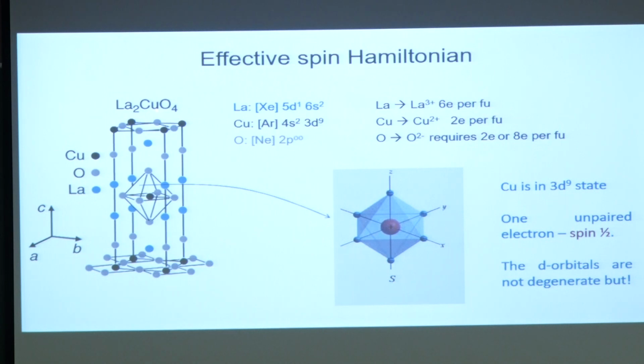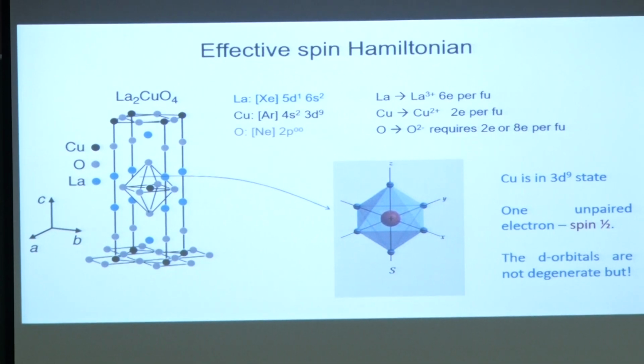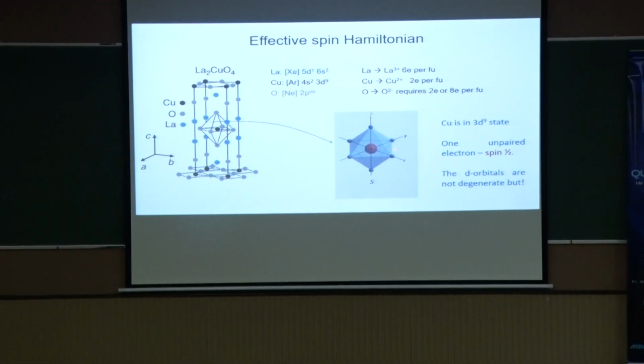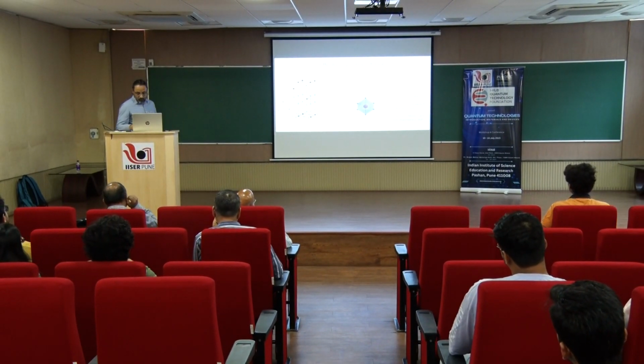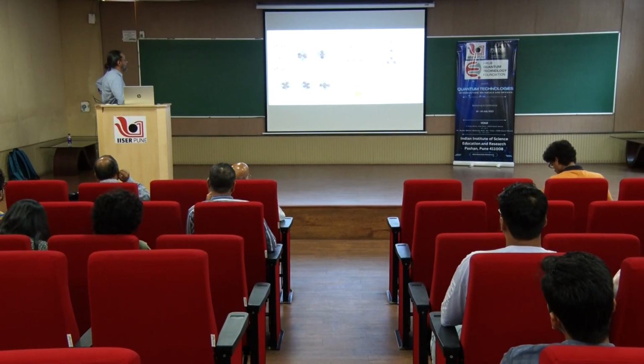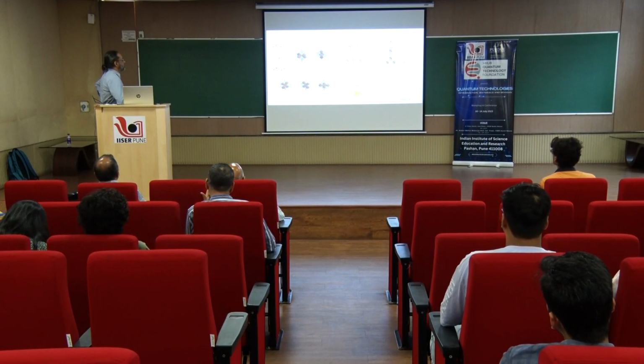So, basically what happens in this compound is that lanthanum has the 3 plus oxidation state, copper has 2 plus because it gives away 2 of its electrons, and therefore, it remains with 3d9 configuration, okay. And 3d9 is basically one unpaired electron because the d shell can take 10 electrons. So, you say that copper has a spin half, but of course, these d orbitals which are energetically degenerate when they are in vacuum no more have the same energy because they are seeing these negative charges around them. So, depending on the orientation of the lobes of the d orbitals, there is a splitting of